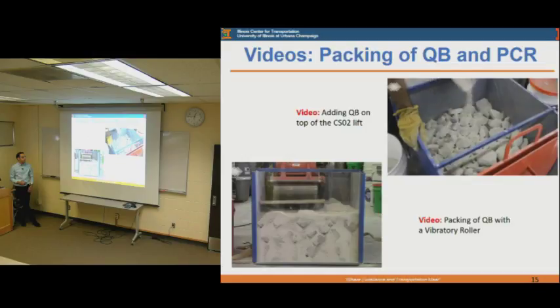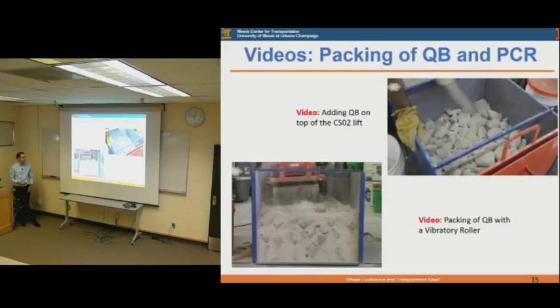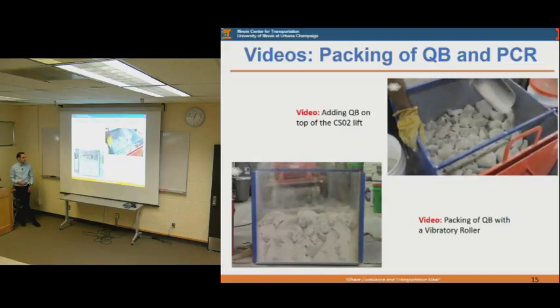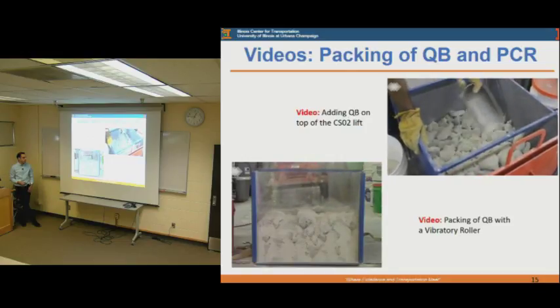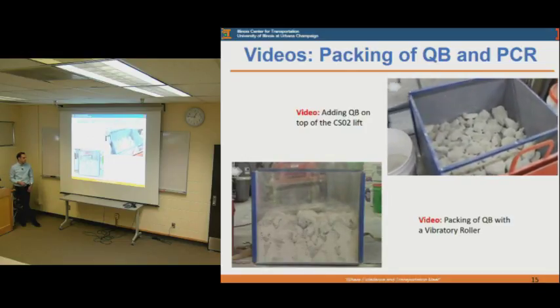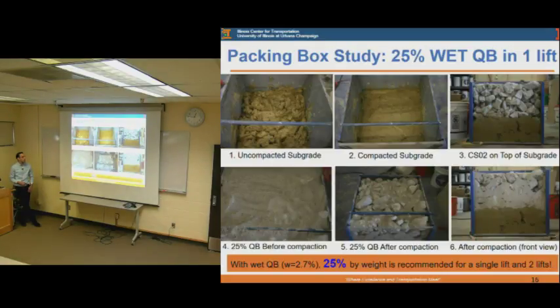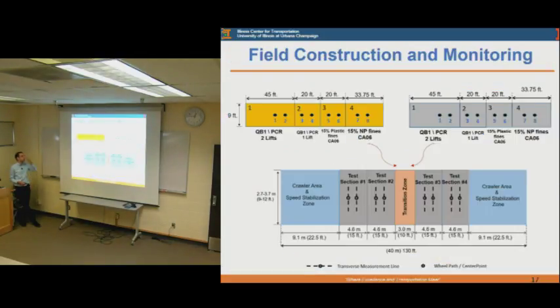So this was more of a qualitative study to investigate the packing. Here is showing how the quarry byproducts were added from the top of the surface, and then this is showing on the left bottom graph the compaction of the quarry byproducts between the voids. So in the lab, it was working, and our conclusion with the different various 14 tests, when we added the soft subgrade that we have and the wet quarry byproduct, is that with a 2.7% moisture content, 25% quarry byproduct by the weight of the large rock is recommended for a single lift and a 2-lift application in the field. And that was the first investigation.